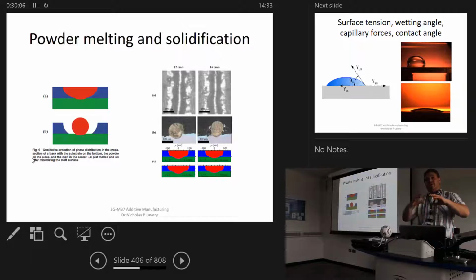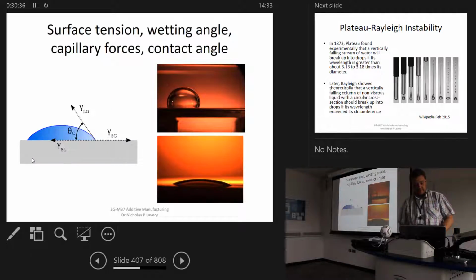tracks themselves re-solidify. So you've got a liquid metal, and liquid metal, like any liquid, has surface tension, which is related to the gas, the atmosphere in which it's at, and also the surface on which it's lying. You can see quite clearly here, in figure B, two melt tracks solidified onto the substrate. You can see one which has got no neck, and the other one's got a neck, and these are both related to surface tension properties.